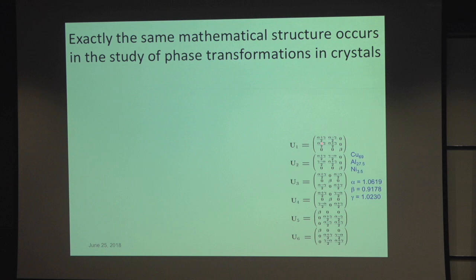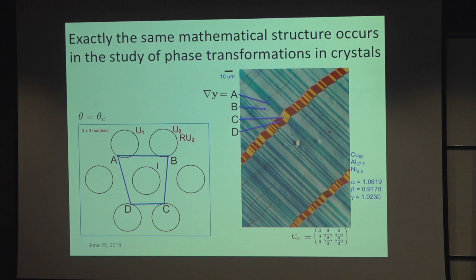So how do you tune? You tune by changing the composition of the material. If the material is some alloy, then you change the composition. You very carefully measure these, and you go towards your mathematically determined lattice parameters. So very good, that's how you do it.